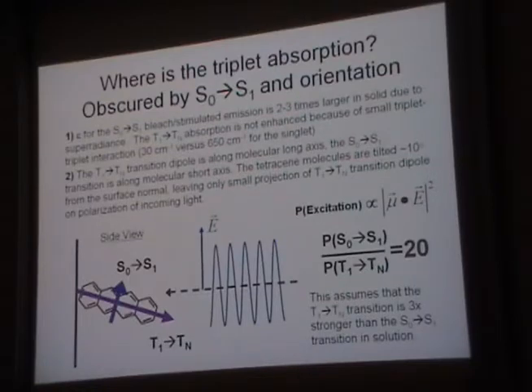But why is the triplet so small? Well, one answer is it's not there. Okay, but we don't like that answer, so we're going to try another answer. The answer is that it has to do, again, with the polycrystalline nature of these films. Tetracene and Pentacene, and Stefan knew this, align on the surface almost perpendicular. They're just tilted at a slight angle from the surface. This is the way these crystallites grow on flat surfaces.